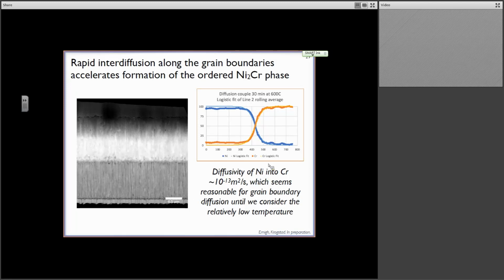In this particular case, I'm showing you that the diffusivity of nickel into chromium is on the order of 10 to the minus 13 meters squared per second. Which, if you look at some of the literature for something like nickel going into a BCC metal like chromium along grain boundaries, is actually pretty reasonable until you pay close attention and realize that we did this at 600 degrees Celsius, when diffusion should be slow, very slow. All right, and so clearly we have some interesting things happening here. I don't have time to get into the details of this, but actually if we go a little bit longer than 30 minutes here, we actually start to see the development of the nickel-2 chromium intermetallic phase, which should take hundreds of hours to start to form.